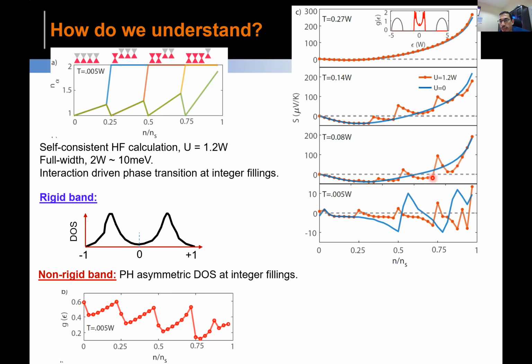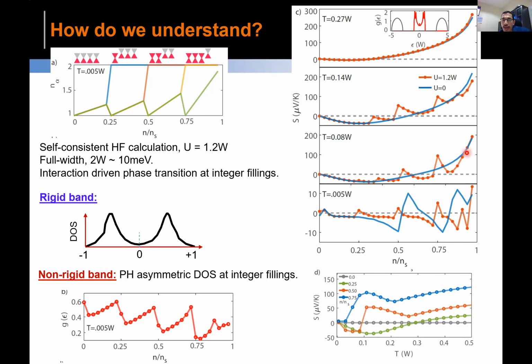The dot with the line is this Stoner-like transition case. And you can see here an integer filling is sort of giving you a glimpse of that, they're able to capture this thermopower. So we believe this is the physics happening, and in fact, theoretically, if you plot the thermopower as a function of temperature, it gives you a non-monotonic temperature dependence. So this qualitatively captures the essence of our work.